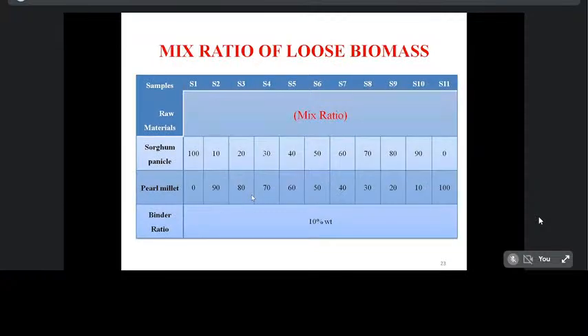For the mixed ratio of loose biomass, I have taken sorghum panicle and pearl millet, and the binder ratio is 10% weight. The two constant solid biobriquettes produced are 100:0. That means 100% of sorghum panicle and 0% of pearl millet, and 100% of pearl millet and 0% of sorghum panicle. The remaining briquettes were produced under various blended proportions, such as 10:90, 20:80, 30:70, 40:60, 50:50, 60:40, and inversely it is mixed, both the sorghum panicle and pearl millet.